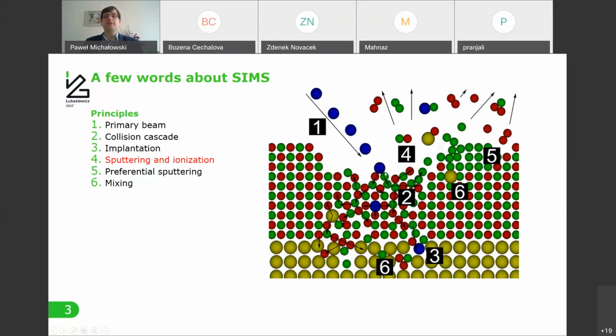So basically, when all these atoms start to move, we will naturally push them down and bring some up, even though they were not present in these particular layers before. As you can see, and as you can imagine, the effect is asymmetrical. We definitely push down more atoms, mix them down, than bring them up. But both effects may occur, and it has to be taken into account to interpret the results properly.